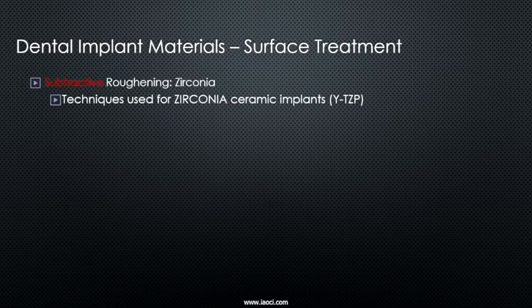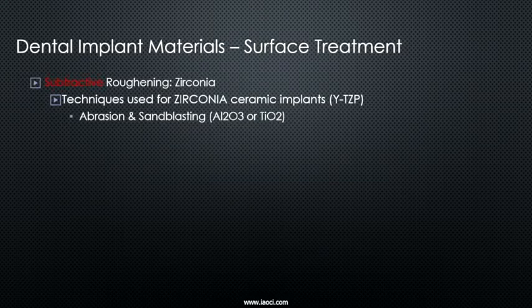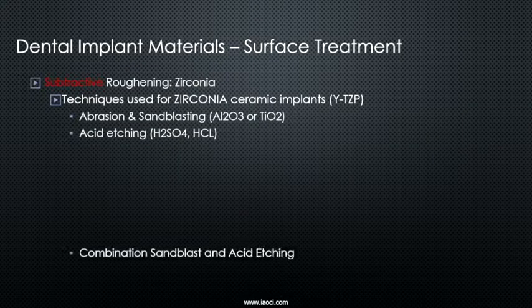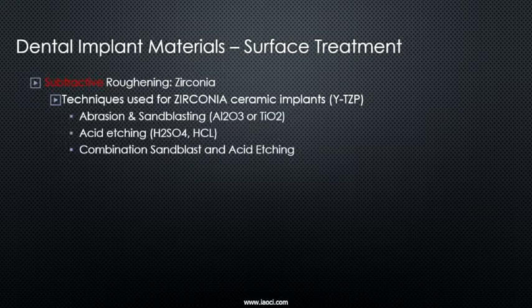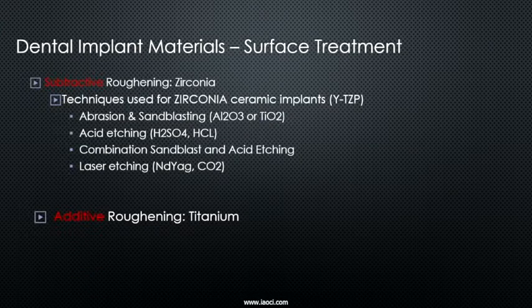Now, osseointegration of zirconia, how does that happen? Well, first of all, you have to understand, zirconia implants do not have any coatings. It's the implant itself that's roughened or treated, and the bone grows into your implant or onto the surface of that implant. Okay? So there's many techniques of roughening implant surfaces. You have what you call subtractive techniques, where you blast the implant and you roughen it by subtracting some parts of it off of its surface. And then you have additive techniques, which do not apply to ceramic implants, where you do the coating. So that doesn't apply to ceramics.